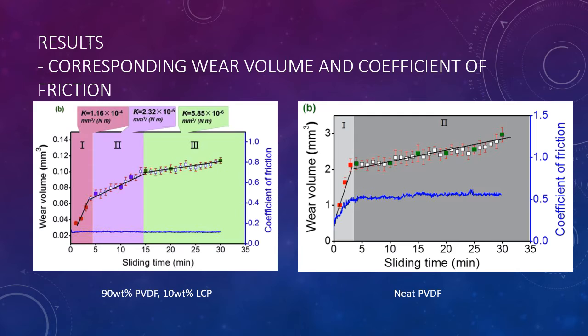So for now, I'm going to present the results of the research. For the corresponding wear volume and coefficient of friction, for 90% PVDF and 10% LCP, we can split into 3 phases. The first one is the running-in phase, because of the initial contact between the surfaces, the wear volume increases more significantly than in the second and third phases. After 4 and a half minutes, we get into the transition phase.